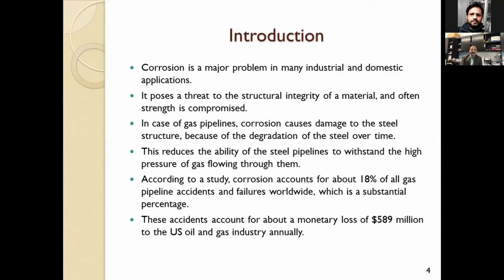The amount of damage which is caused by corrosion is significant, and we see that about 18% of all accidents which happen in the industry are because of corrosion related problems. This degree of damage also has a financial loss, which amounts to $589 million according to a study carried out by NACE International.